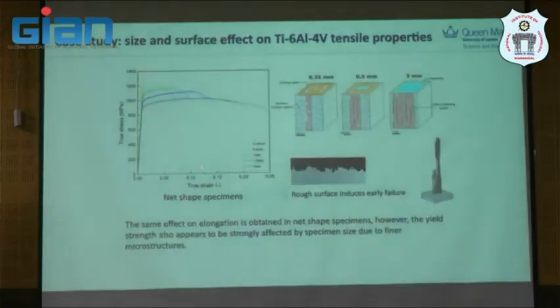And this is due as well to the solidification point of view. So it's not just printing as printing. You need to rationalize why it happened like that. Why the surface roughness and solidification structure may contribute to the property that you see. So the argument is that for the smaller sample, the dendritic arm actually comes from the side, and then it traps the columnar grain in the middle, whereas in the bigger sample, you get more columnar grains, which is more detrimental for property. And that's what they found. And you can follow this work as well in the paper.